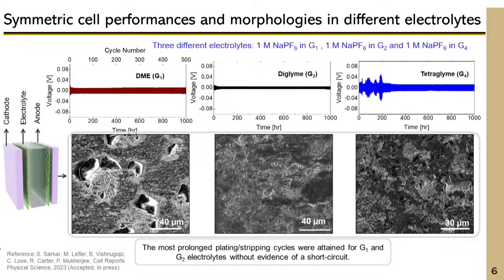The first thing we want to see is how the cycling behavior looks. When you make the battery with these electrodes under different electrolytes, will they be long-lasting, go into short circuit mode, or die? So we looked into the cycling mode, and the first 2 basically show you do not want any kind of erratic voltage pattern in the curve. We saw that monoglyme and diglyme had very stable, smooth performance. But tetraglyme, at the early cycles, started to show erratic voltage patterns up and down, an indication of short circuit. That means we might have the possibility of dendrites in this particular electrolyte.